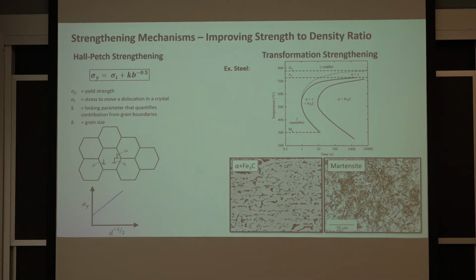Another way to strengthen materials, closely related to the previous method in the case of steel, is transformation strengthening. With steel, if you want to strengthen a eutectoid steel, a hypereutectoid steel, or a hypoeutectoid steel with a lot of carbon but not past 0.77, you can take these materials and heat them up. They turn to austenite, then you quench them.